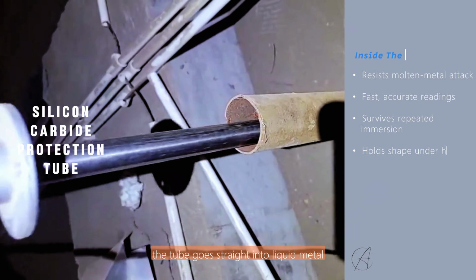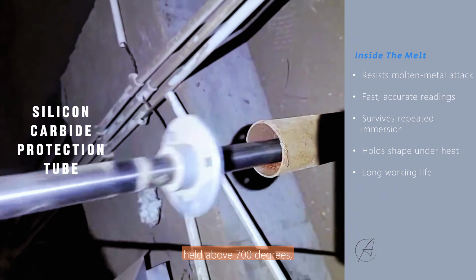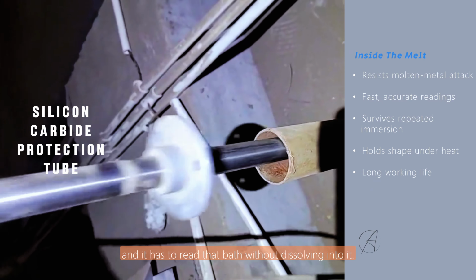In a non-ferrous melting furnace, the tube goes straight into liquid metal held above 700 degrees, and it has to read that bath without dissolving into it. The same corrosion resistance that shrugs off acids keeps molten aluminum and zinc from eating the wall, so the sensor stays clean and the reading stays honest heat after heat.